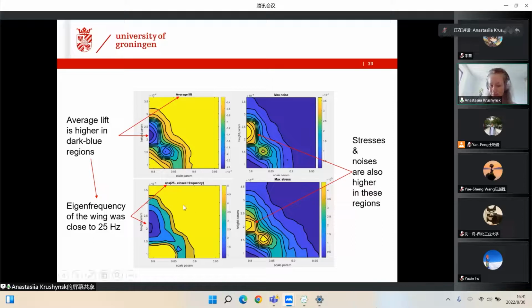Specifically, yellow color shows that we are about 5 Hertz away from the excitation frequency, while dark blue color says that we are very close to the excitation frequency. And you see this dark blue region here, that corresponds to the parameter values where the eigenfrequency of the wing approaches the excitation frequency.